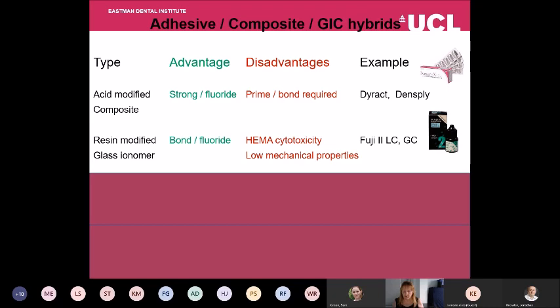What companies have been trying to do is produce a wide range of different hybrids. So some of the early hybrids were the acid-modified composites or the resin-modified glass ionomers. The acid-modified composites are strong and they provide some fluoride to try and encourage remineralization, but you still have to have the prime and bond steps to get the material to stay placed. The resin-modified glass ionomers, their benefits: they do bond like a GIC, they do release the fluoride, they have much better strength than the conventional glass ionomer, but they contain HEMA. The resin is HEMA, which is cytotoxic.